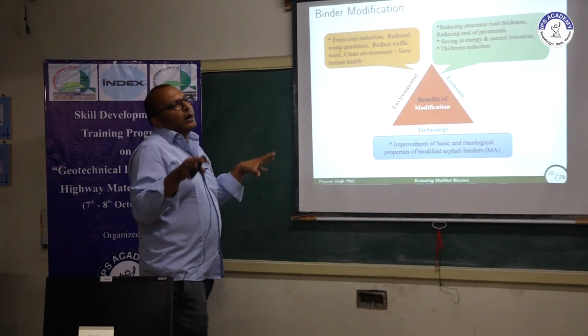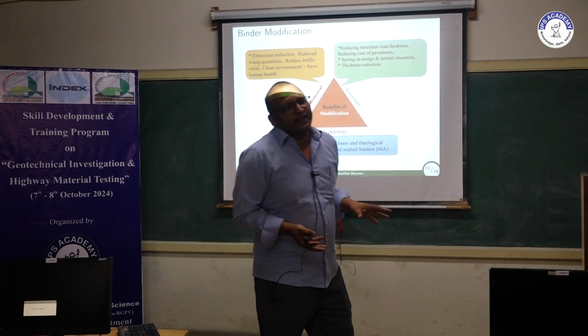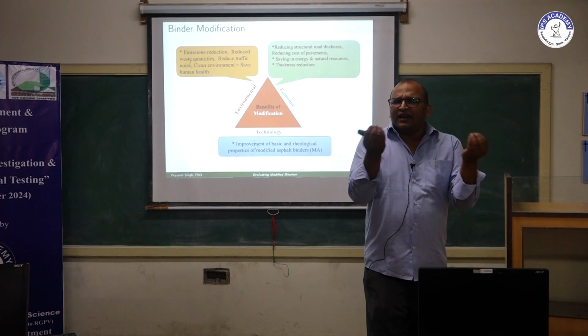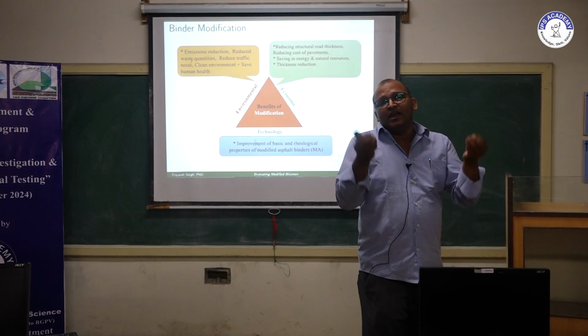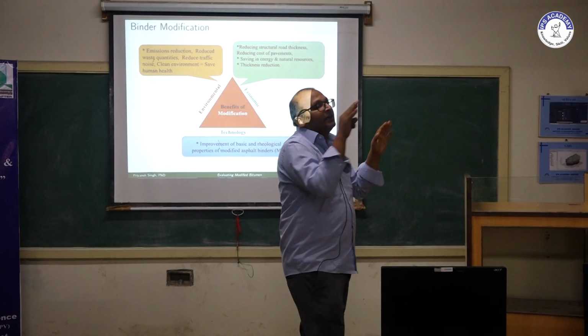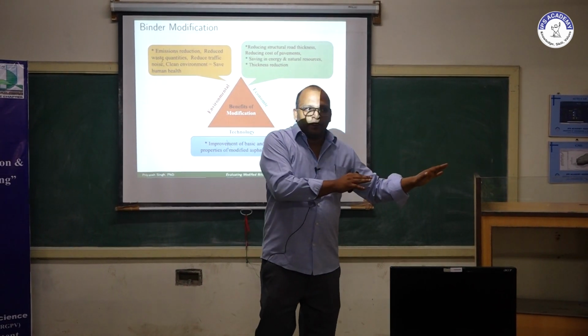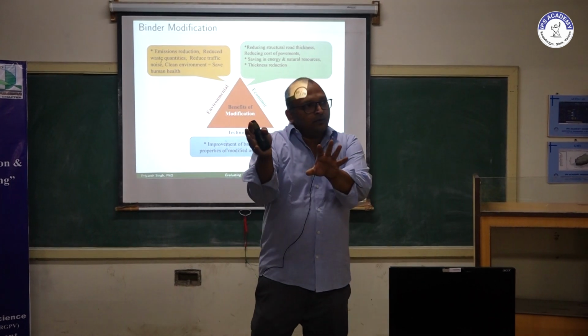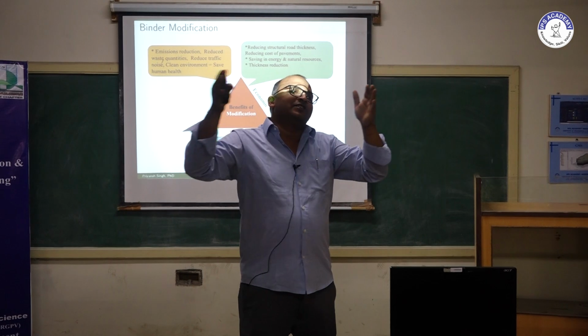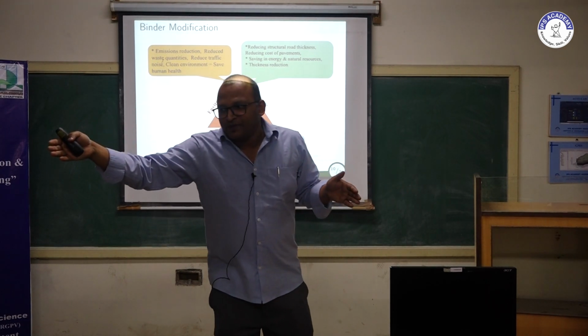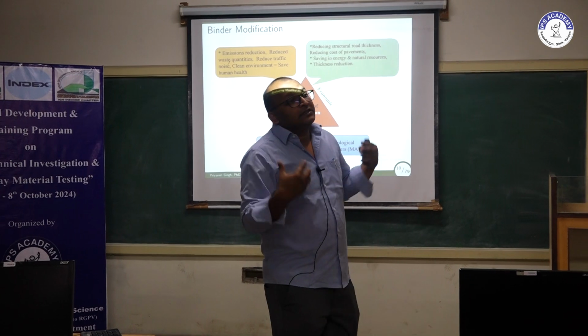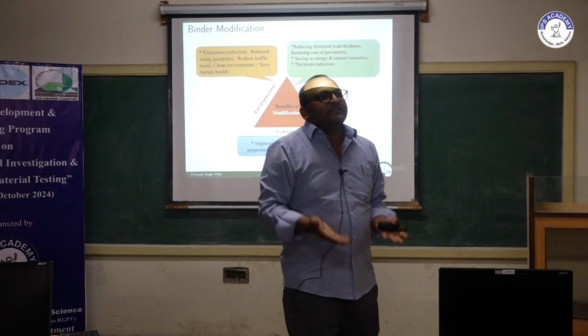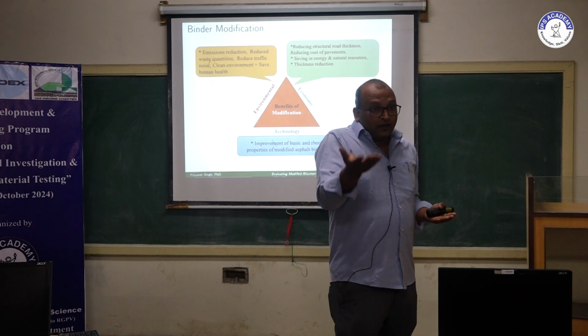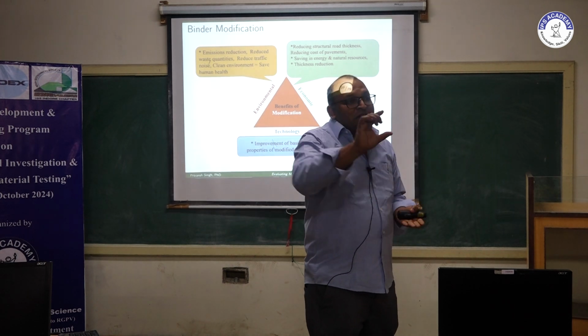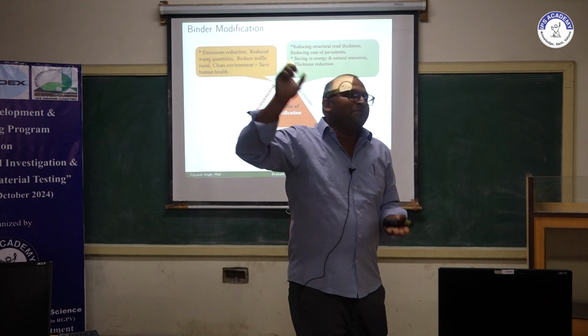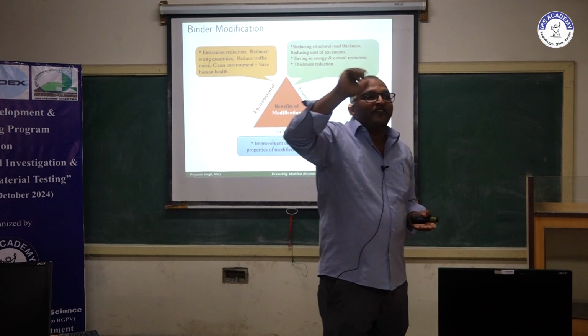Now, whatever the existing binder we have, why do we need any modification in the binder? When I say binder, or neat binder, or bitumen, it means it's just the raw extract we got after distillation from the petroleum product. That is processed by the refineries to meet your viscosity grading, maybe VG 10, 20, 30, 40. But nowadays temperatures are reaching extreme levels. We are seeing air temperatures of around 49, 50, so the pavement temperature will be a little higher, maybe hitting around 53 or 55 degrees Celsius.